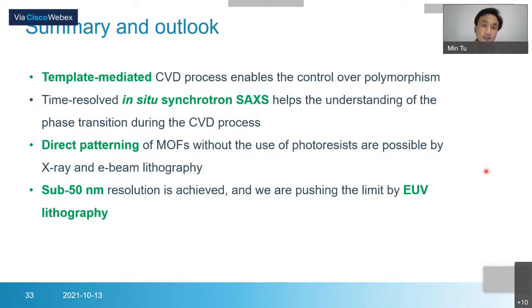First, on the MOF film deposition, we developed a template-mediated CVD process to control the polymorphism, and we also used in situ synchrotron SAXS to help us understand the phase transition during the CVD process. We also developed direct patterning of MOFs without the use of photoresist by X-ray and E-beam lithography, and we achieved sub 50 nanometer resolution and used it as a chemical sensor.